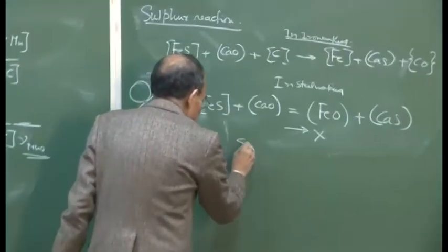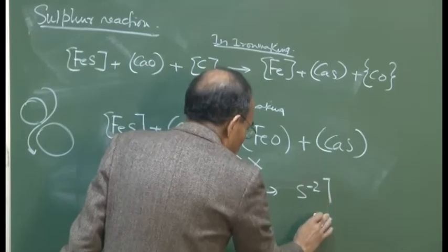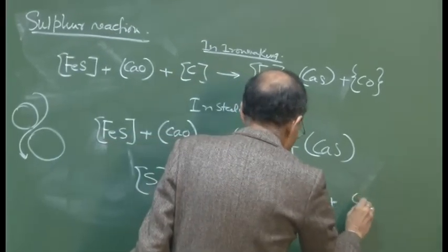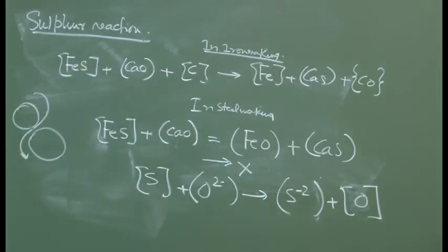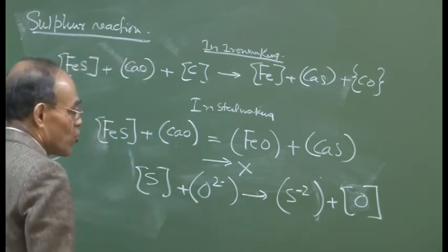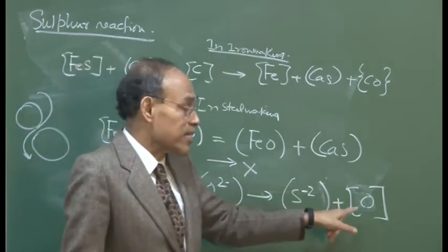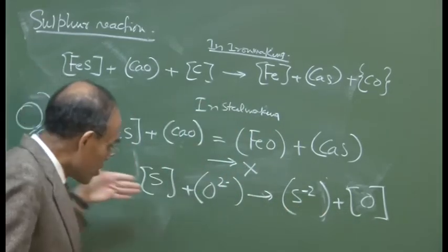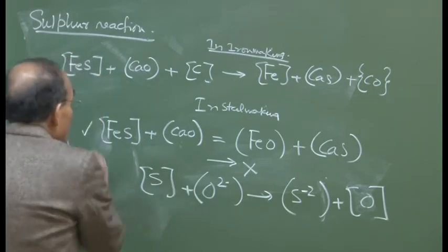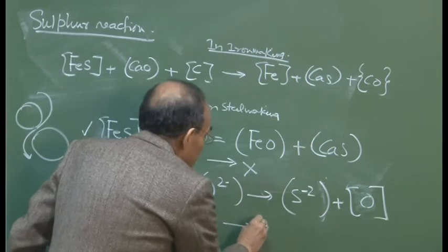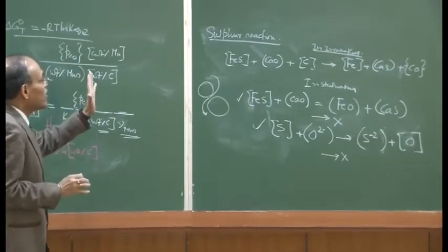And this reaction, as we have indicated, is sulfur in the metal, and this is the molecular and ionic form of the equation. This is in the slag and this is in the metal. But whether I write it in terms of oxygen in the metal, this reaction really is not going to take place much, because the activity of oxygen, as per the carbon-oxygen diagram you remember, increases as the carbon content goes down, and as a result this is already large. So there is an inherent tendency to oppose this forward reaction by the strong backward reaction because of the large concentration of dissolved oxygen in the system. Whether you write this equation or that one, they are one and the same equation. I would like to conclude today's lecture by saying once more that steel making is not the site for a significant amount of desulfurization. Beyond that, we will not discuss anything.